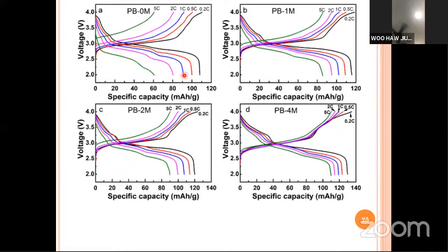Now, for 1 C rating, this is the blue color, getting about 90 plus. As we increase the C rating to 5C, the performance is poor, about half of the value. Now, as we are preparing the PB from 0M to 1M, 2M, and 4M, we observe that the performance at high C rating is getting better and better. Let's look at this PB4M. Now, the 5C rating, which is the green line, is quite good actually, right? Compared to the lower C ratings, not much different, maybe 10 to 20% drop instead of 50%. So we are very happy about this.